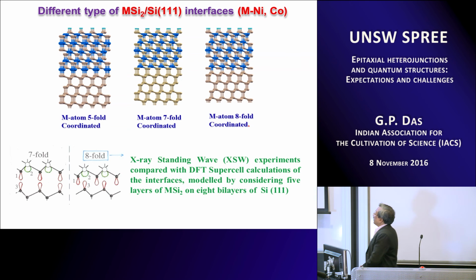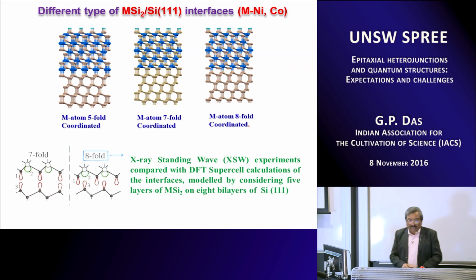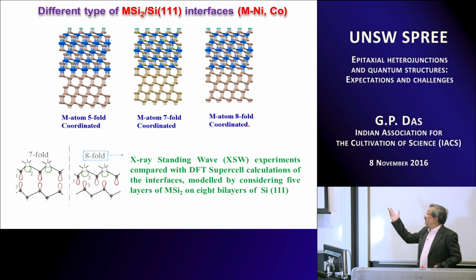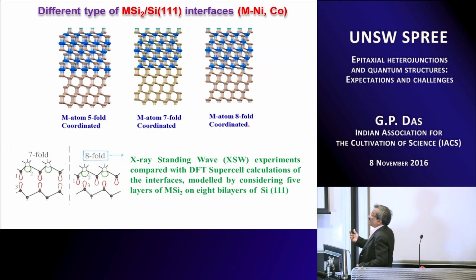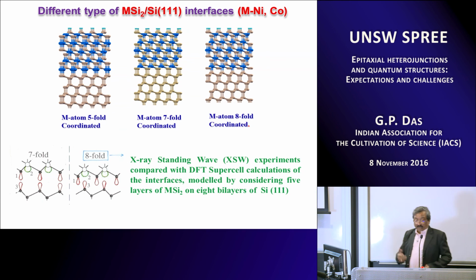These X-ray standing wave experiments have shown whether, in the case of nickel disilicide on silicon, it is 5-fold or 7-fold or 8-fold coordinated. And I will tell you the result. In the case of nickel disilicide, it has been established using X-ray standing wave that it is a 7-fold coordinated structure, whereas in the case of cobalt, an 8-fold structure has been established.